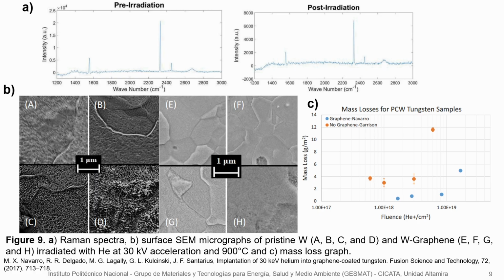Also, the mass loss analysis shows that the samples with graphene lost less mass after the irradiation. The Raman spectra before and after the irradiation show no modifications in the G band and D band, and also in the 2D band. This is attributed to no damage being present after the irradiation.